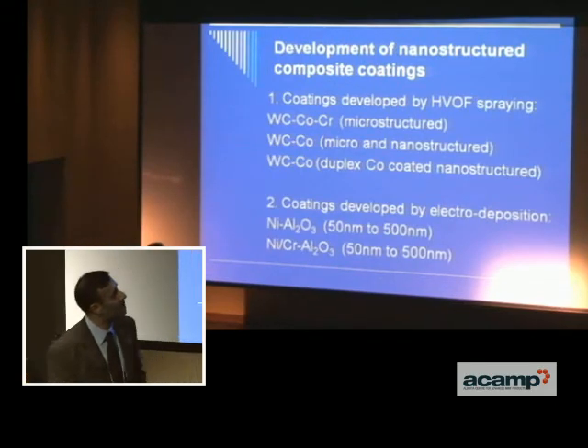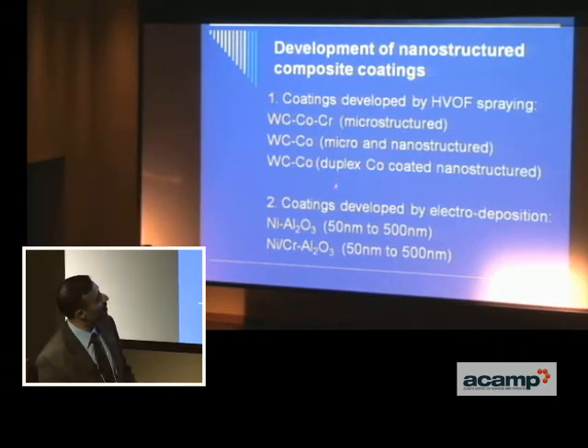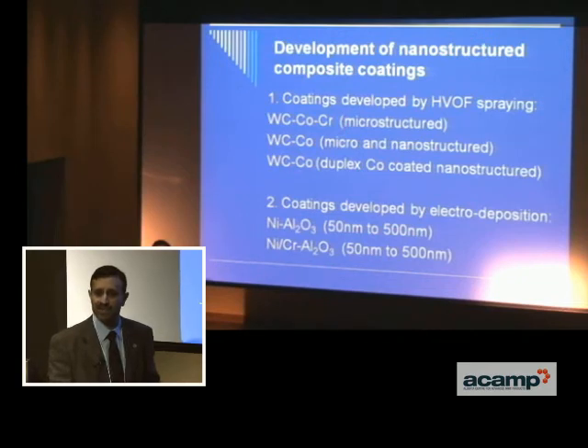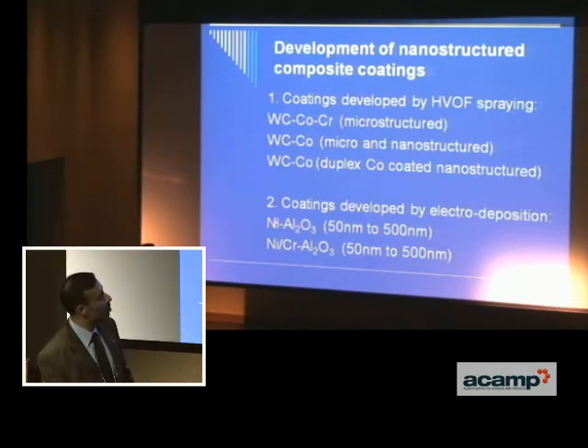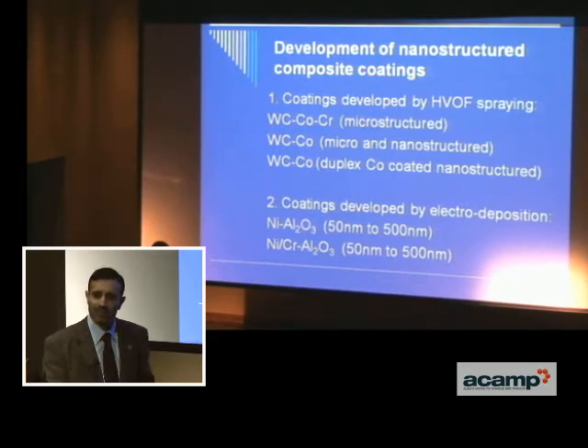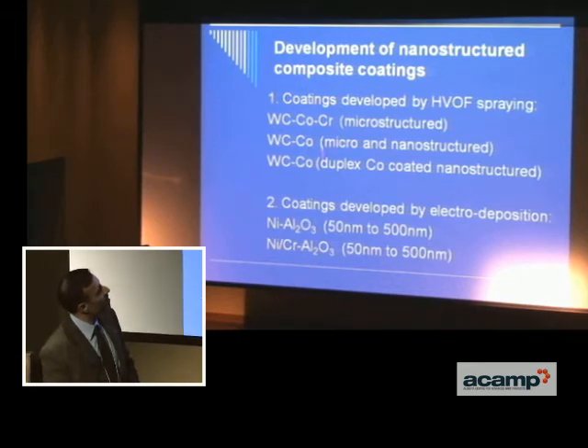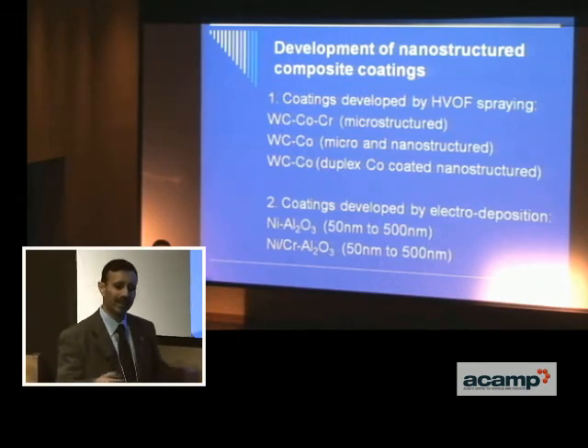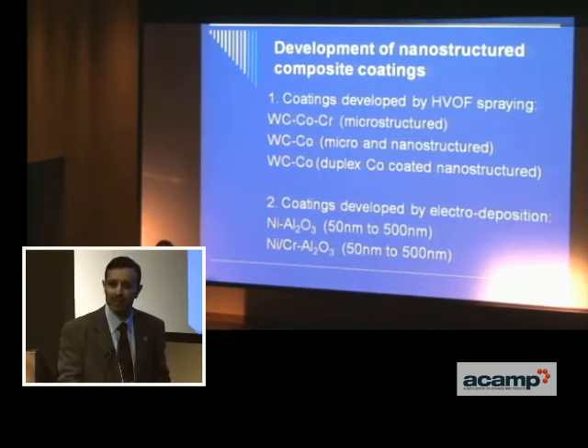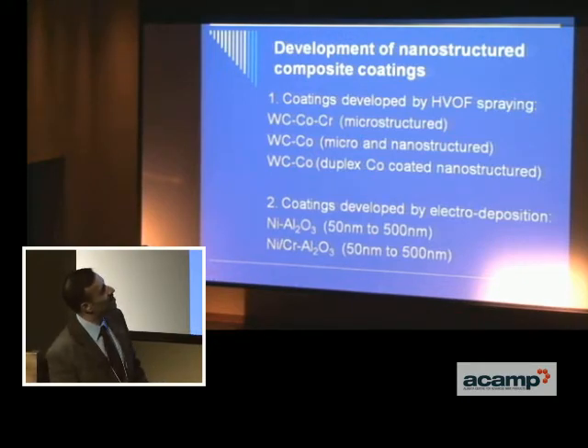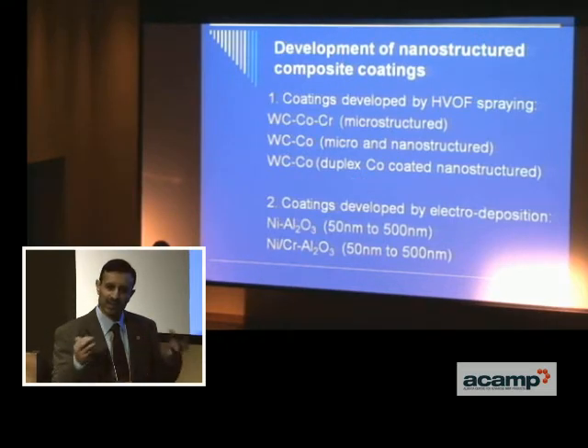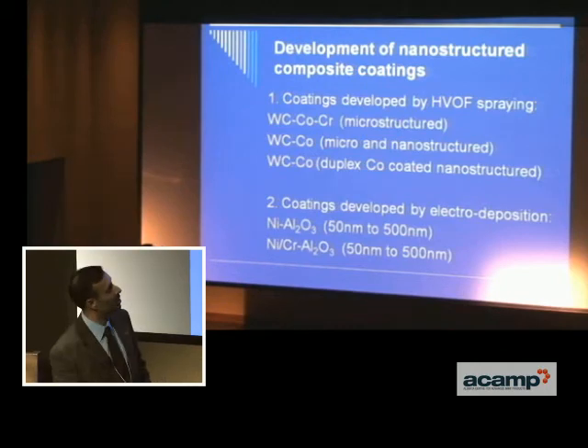So at the university, we're looking at two separate regions. One is the use of WC, tungsten carbide based materials, and also we're looking at some more novel coatings where we want to be able to treat inside pipelines as well. We've got listed here different compositions. In fact, there's a wider number of families of compositions that we're looking at, but there are patenting issues and we need to deal with those before I can talk about them. But certainly there are novel types of coatings that we're using where we're using these special kinds of coated powders, duplex coated materials.